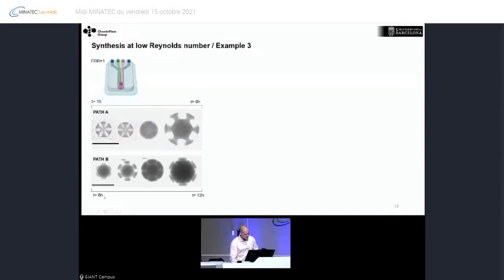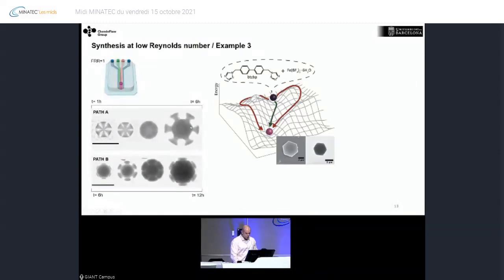But then from 6 hours to 12, it looks like the hexagons are now growing from the face, not anymore from the vertices. So what we thought when we observed that is that, given the energy landscape, this is the thermodynamic pathway that allows the formation of this hexagon. So there are two other pathways that we are unveiling by doing the reaction in these controlled reaction-diffusion conditions that we have in the microfluidic device.